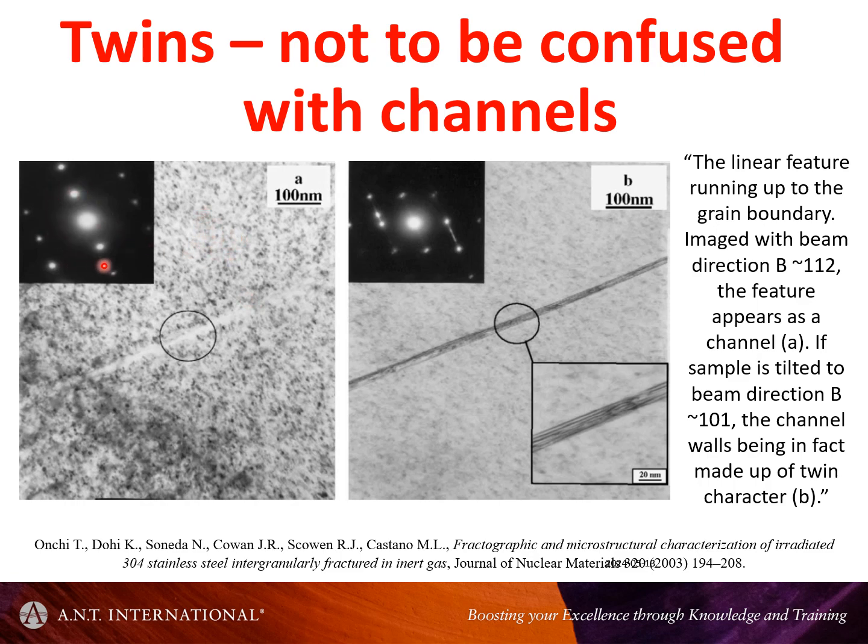So if you have a diffraction condition, as we show here, which is just suitable to show contrast, and I'm not going to go into a lecture on TEM, but it would require a lecture on TEM for you to get that, but just take my word for it. The diffraction conditions one sets up in an electron microscope, you set up particular direct diffraction conditions so that you can image defects like dislocation loops. And these dislocation loops might still be here, and in fact they probably are in this region, but the crystal has a different tilt at this point. And so we're not in the same diffraction conditions, and you don't see them.